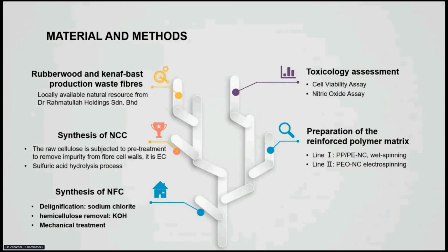For synthesis of nanocrystalline cellulose, pre-treatment is needed to extract cellulose from the fiber cell walls. After that, we use sulfuric acid for the hydrolysis process. For nanofibrillated cellulose, first of all, delignification removes the lignin content of the raw biomass. Later on, we use hemicellulose removal. After that, we use mechanical treatment, milling the extracted cellulose. We also do toxicology assessment, cell viability, and nitric oxide assay. In the end, we use the prepared nanocellulose to reinforce a polymer matrix.